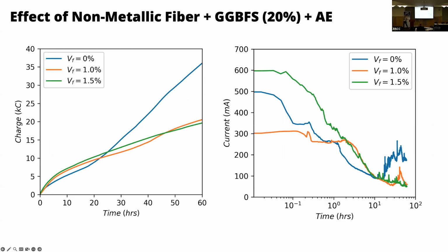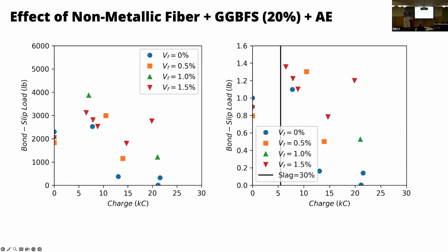On top of the slag concrete, we tried to use basalt fiber. So how is it used? Can you see that? The blue response is normal concrete. As long as you use the basalt fiber, the curve is a little bit lower than that, which means it is stronger against corrosion. I believe that the fiber somehow minimizes micro cracks as well, so that slows down the corrosion process. As a result, the bond strength is higher when you use more fibers in there.